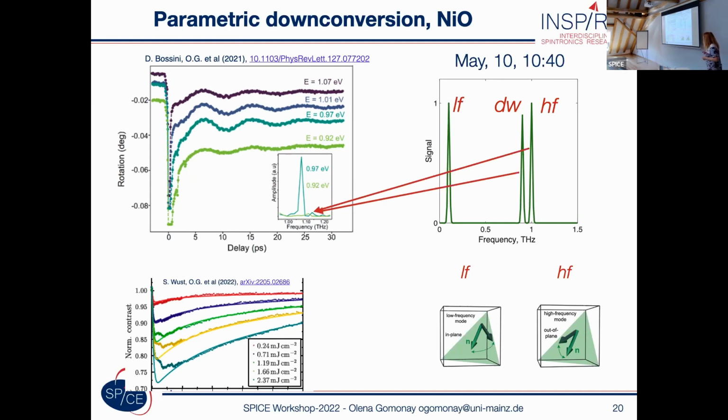So this is a kind of ultrafast demagnetization. Application of quite strong optical pulses which heated the sample induced the reduction of the magnetic moments of nickel oxide, but as a consequence, we can anticipate that also magnetostrictive effects were diminished, and this process can facilitate switching to the other state.